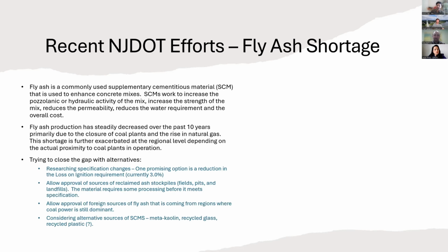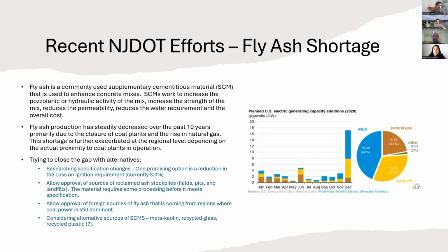So what's been happening is, I think Dave mentioned reclaimed ash. We have 2 sources of reclaimed coal ash. They estimate they have about a 15 to 20-year supply. There are countries in the world still using coal, so we're getting coal ash from India and Southeast Asia. They're bringing it to our market. But that's not sustainable in the long term, so we're looking for other sources. We're looking at ground glass. We're looking at other things that can essentially act as a pozzolan for concrete production.